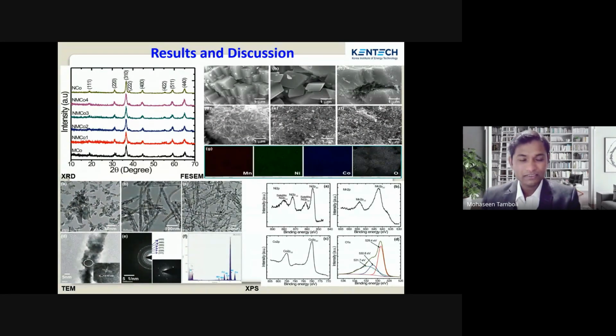Then figure C shows the NiCo2O4 porous nanostructures. When we measure the surface area, the 60% nickel in MnCo2O4 porous shows a high surface area as compared to the MnCo2O4 porous and NiCO2 pore. In the high resolution images, there is a porous structure, and figure E shows the selected area electron diffraction pattern, and all the planes are very well matched with the XRD planes here. Then again figure F in the TEM section shows all the elements here.